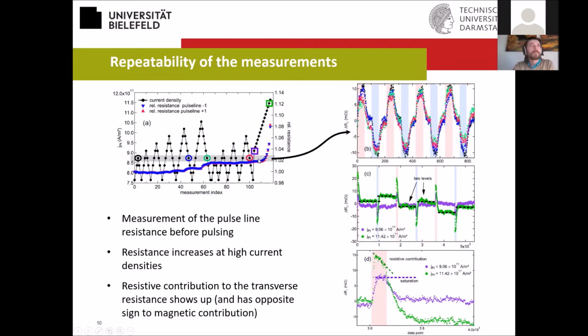Okay. And at the same time, we observe that the pulse line resistance, which is basically just the resistance measured along the pulse lines, increases as we go to higher current density. So you see these nice steps here when we increase our current density past a certain threshold value, which is around 1 × 10¹⁰ amps per square meter. As we go higher, we see that the resistance in the pulse lines increases. And here, finally, we just cranked up the current until the device ultimately broke. Okay, so it seems that this additional contribution that we're getting here is related to this increase in the resistance.